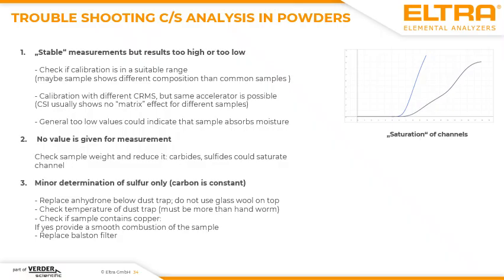When the sample absorbs copper, it could mean that you have to again contact ELTRA because we have to provide a very smooth combustion. When you release by an intensive combustion copper oxide, this copper oxide also absorbs SO2, and this could cause a minor determination. The last error of, I would say, minor determination of sulfur, which is also typical for this kind of analyzers, is a worn Balston filter. When it's worn and contains some moisture, you also have the effect of absorption of SO2.